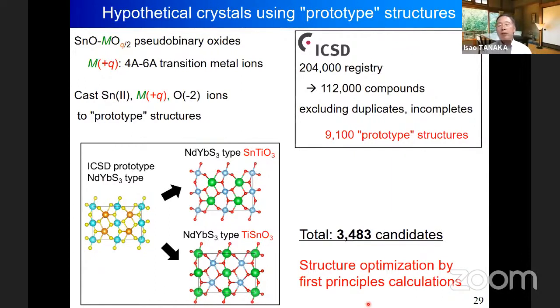So our strategy is shown here. We again use ICSD, but we use prototype structures registered in ICSD because we are interested in novel materials, and those crystals which are already registered in ICSD are not of our interest. We just borrowed prototype structures from ICSD data, something like this type of structure or perovskite structure, spinel structure, rock salt, whatever. And in this case, we cast these elements into this structure, in this case, tin into one cation site, titanium to the other atom site, or titanium to the one site and tin to the other site. And after substitution in this way, we optimize the structures and obtain the first principles energy.